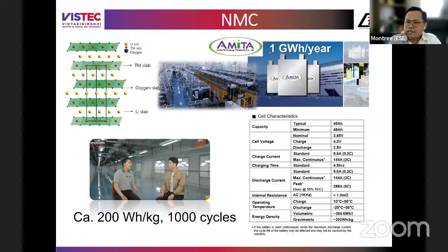Look at NMC from Amita. On their website, they have 50% nickel, 30% manganese and 20% cobalt. They call it NMC 532, but the structure, we have layered material. We don't have phosphate as in LFP, so we get 60 watt hour per kilogram higher than LFP. So roughly 200 something, depending on the anode that they use. If they go to LTO, they get less energy density, but they can get faster charging.